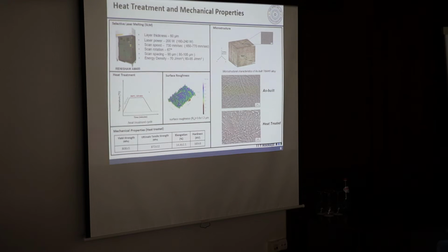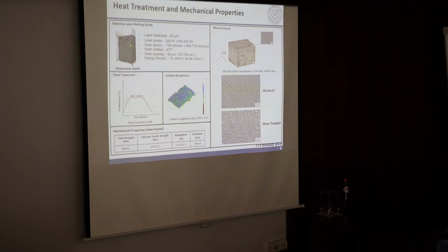Now, these are the process parameters that we have used. We printed the specimens in 60 micron layer thickness, and we know that the as-fabricated specimens have higher residual stresses, so we did some sort of heat treatment. The heat treatment was selected based on our previous study. We did heat treatment at a temperature of 850 degrees centigrade for 2 hours in a high vacuum furnace.